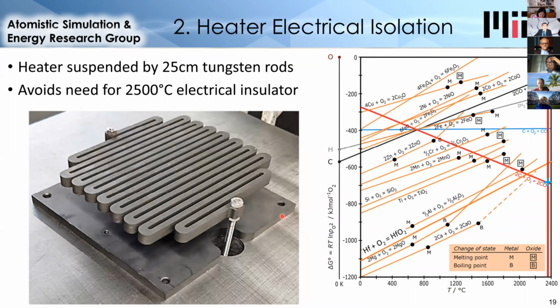So instead of trying to put a solid between the heater and the base beneath it, we just used a more rigid heater material, which was graphite. The reason it's more rigid is that its resistance is higher, so it can be made thicker. This isn't necessarily a problem at the large scale, but was a challenge at the smaller scale we're doing experiments at. And so we used this graphite heater that was just suspended by these tungsten rods, and therefore we avoided the need for a 2,500 Celsius electrical insulator.